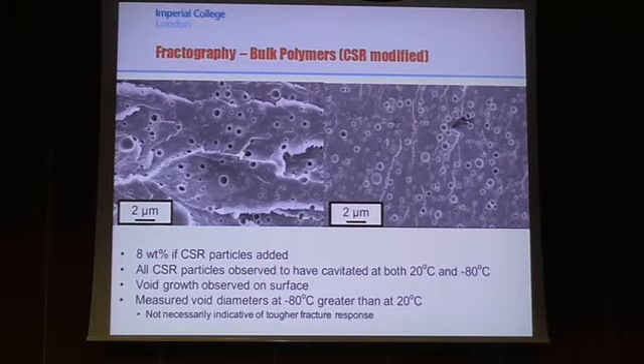Okay, so let's have a look at the fracture surface of the CSR modified bulk polymers. On the left-hand side, we have the room temperature, 20 degrees. On the right-hand side, we have the minus 80 degrees. We can see that all the CSR particles are cavitated at both 20 degrees and minus 80 degrees. Slightly rougher surface here. There's void growth observed on the surface. If you measure all these voids, they're on average bigger than the particle size, so that indicates that the particles have grown. This is a major toughening mechanism.